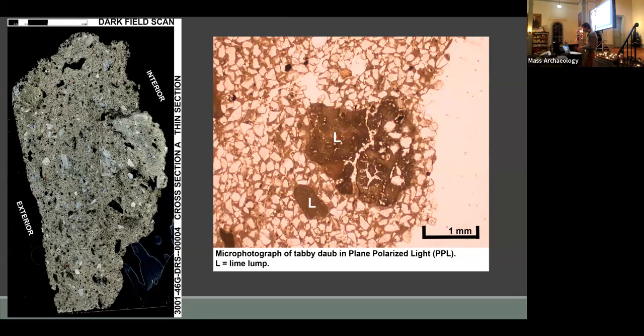And so mechanical differences between mortars using lime putty and mortars using hot mix are not well understood, although the benefits of hot mixing are largely related to faster production and application at the cost of better control over mixing proportions and uniformity. And some material scientists report that hot mixing can result in a stronger lime mix. So after slaking and stirring, sieving was done to remove lumps and unslaked lime and to even incorporate the aggregate for further consistency and texture.